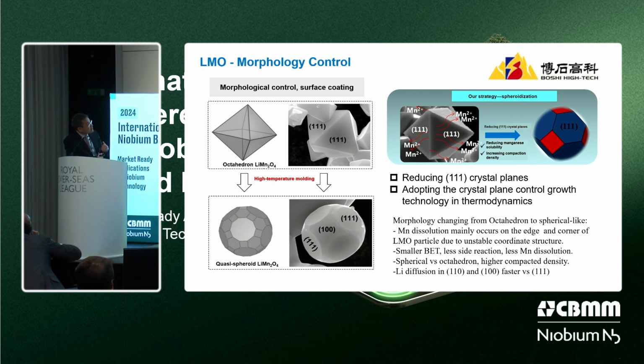First, as people know, for the niobium-free LMO, the lattice plane is this 111. And if we increase the niobium, we can get almost a spherical-like shape. And this shape has a lot of benefits. First, you can get a smaller BET, the surface decreased. With the same volume, this shape and this shape, this one has a smaller BET. So you have less side reaction and then less manganese dissolution.